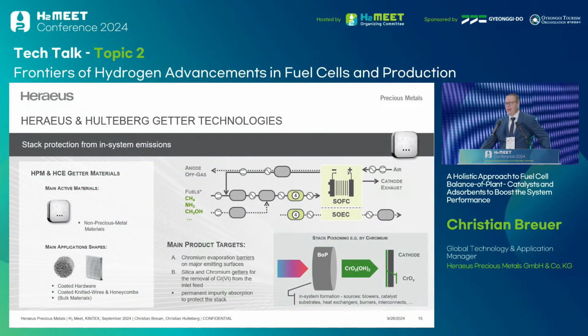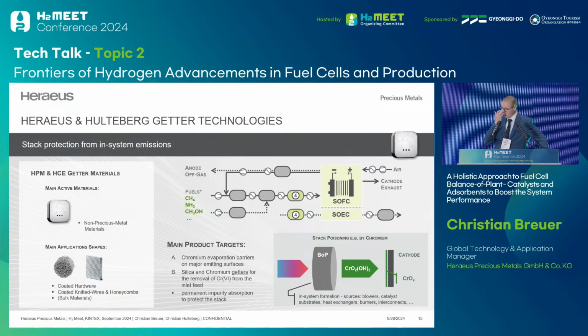Another important topic is the getter materials. I mentioned that chromium and silica poisoning can be challenging for the operation of a stack. So we can apply specific getter materials to the upstream components that could either help as an evaporation barrier, for example for chromium, or get these materials from the gas stream. And you see as well, we can apply them on different geometries, as filters or as coatings on hardware, to then exactly perform these